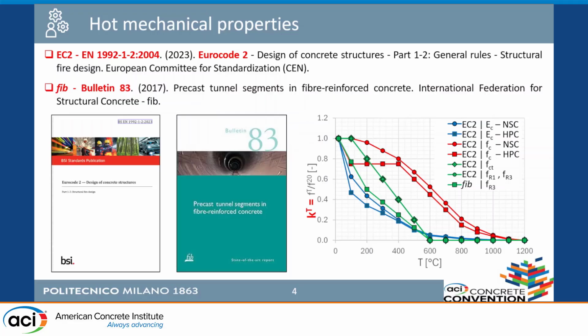So what we see here is a strong decrease of the Young modulus, because since Eurocode 2 takes into consideration also thermal creep, we have a further decrease of the deformation. Finally, going to the green line, we have the decay of the tensile strength. This line is given by the Eurocode 2, in which practically they give the same curve for the cracking stress of the matrix and for the tensile strength of the fiber-reinforced material.